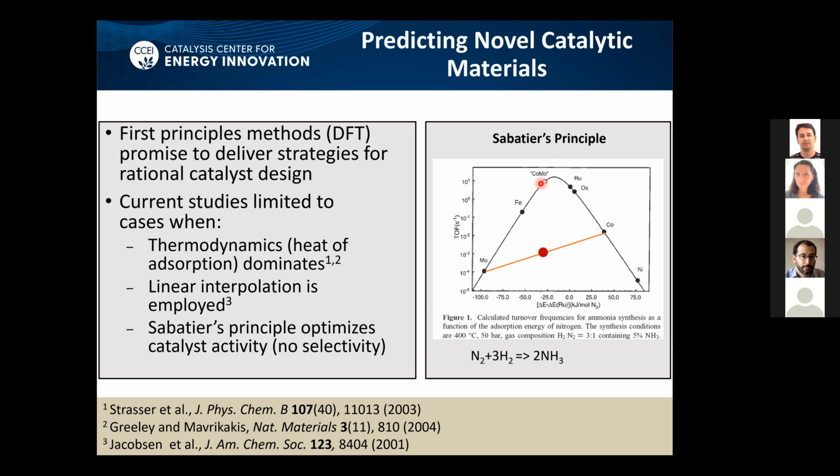So this is the cobalt molybdenum catalyst. They predicted this to be actually better, and they tried that in the lab, and in fact showed better performance than ruthenium, which is a kind of expensive element to use. So basically the idea here is to use the interpolation principle, right, and start predicting new compositions of matter, so we can have new materials.